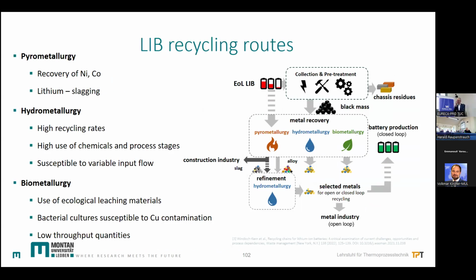So there are different routes. We have pyrometallurgy. The advantage is you can recover nickel, cobalt. The disadvantage is the lithium goes into the slag and not into the gas phase, so it's not possible to recover it. Hydrometallurgy, we have high recycling rates, so colleagues in Leoben, non-ferrous metallurgy, work in this field. There's a high use of chemicals and many process stages to come to this performance. But they are quite flexible to different input flows. And there's also biometallurgy possible. You use ecological leaching materials, bacterial cultures susceptible to copper contamination, but the throughput is quite low.